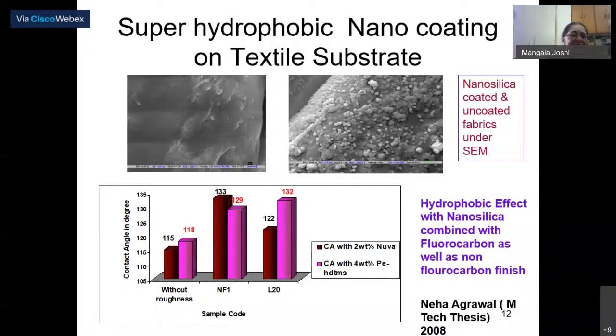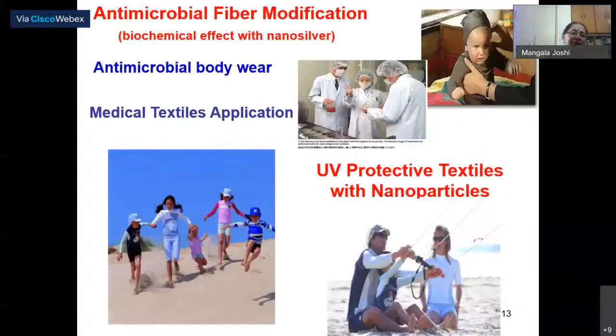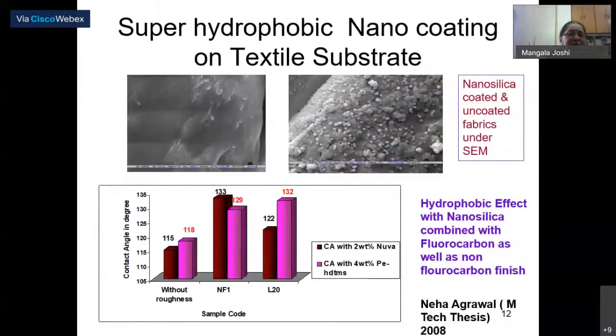If you look at the table, you can see the contact angle. If you just apply a fluorocarbon finish without the nanoparticles, you get a contact angle of 115 and 118. But as soon as you apply nanosilica and create a roughness on the textile, and then apply a fluorocarbon finish, we have been able to go up to 132. Definitely we are not very near nature, but at 132 this fabric was showing a super hydrophobic effect. So this is how SEM, the scanning electron microscope, helps us look at the deposition of nanoparticles on fabric surfaces.